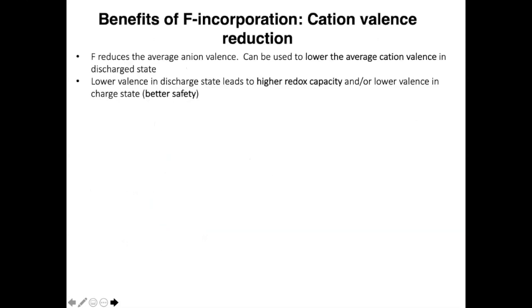Fluorine incorporation does remarkable things for you. I would say the first one is important. It reduces the average anion valence. And of course, that means because of charge balance, it lowers the average cation valence in the discharge state. And so that's good because that means if you charge the same number of electrons, you end up in the charge state in a lower valence. And lower valence is better. It's more stable against oxygen release. So either you can go to a higher capacity, or if you do the same capacity, you end up in lower valence, and therefore you will have better safety.